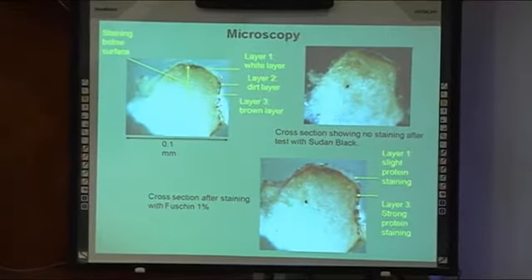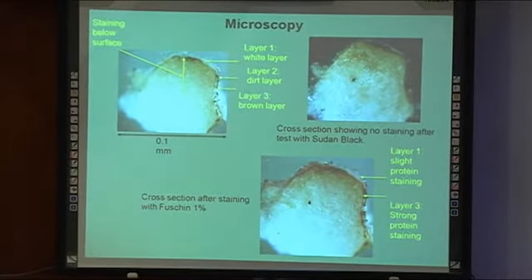A cross-section was then made to confirm what I found with the UV. A cross-section was made of a sample taken from an area on the cast with a yellow staining. Observation under magnification 20 revealed how far the staining had penetrated below the surface. In order to identify the staining material, a protein and oil test was done. The results indicated the presence of protein on the surface of the cast, but not of oil. Neither of the tests affected the deep yellow staining underneath the surface.